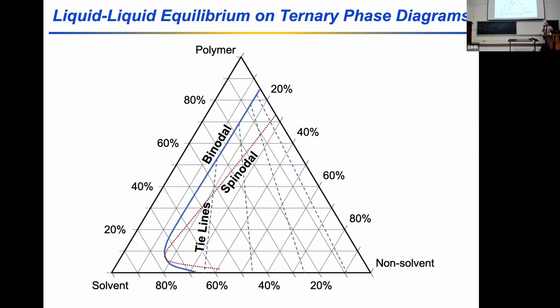Importantly, when we execute this non-solvent induced phase separation technique, the polymer and the non-solvent are not miscible with each other. And so that blue line that shows up, labeled the binodal, indicates the phase equilibrium. If I'm inside of that blue region, that blue parabola curve, that's where I'll form two phases, a polymer rich phase and a polymer poor phase. And the phase that you form is determined by which tie line you land on, and then you just phase separate on the tie line.